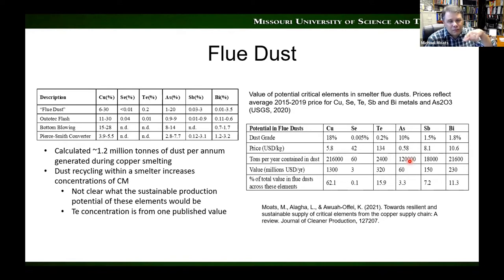And since the dusts are recycled, it's not clear what the really sustainable production rate would be if we magically took all the dust out and treated it to recover the arsenic, antimony, bismuth, selenium, and tellurium. I'm not really sure if those concentrations are real, or if they would drop because you're not recycling and have a recirculating load anymore. But we took the information that we had and tried to guesstimate what this would be. And so you can see there's maybe some value in the tellurium based on one number, and probably the bismuth. That would be what you would target if you wanted to treat your flue dust.